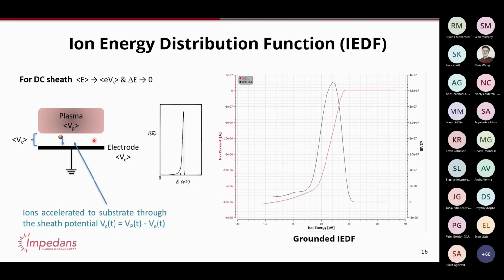Okay? So what happens is the following. Your plasma sits at some sort of plasma potential, usually some small positive voltage with respect to the chamber ground. So 15 to 25 volts, or this sort of range, is very typical. So that means if the electrode is at 0 volts and the plasma is at plus 20, let's say, then ions will accelerate out of the plasma and hit this with 20 eV energy. So 20 volts, one charge of 1 e, is 20 eV. So when there's what we call a DC sheath present, you get a single peak of ions.